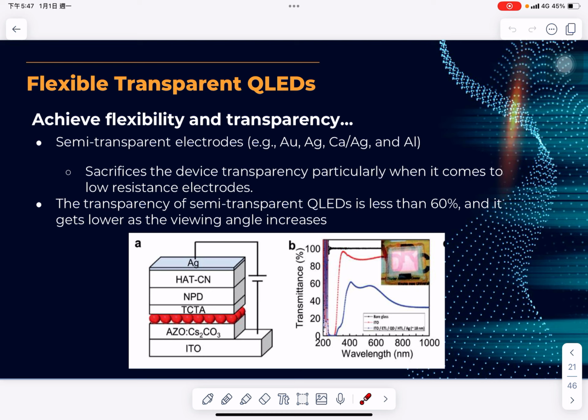Thin metal films like silver, gold, calcium, and aluminum act as semi-transparent electrodes in flexible transparent LEDs, like this structure in this figure. Reducing film thickness maintains light emission colors but decreases device transparency, notably below 60% in semi-transparent QLED, dropping further with wider viewing angles. Like this, you can see the experiment result in this figure.